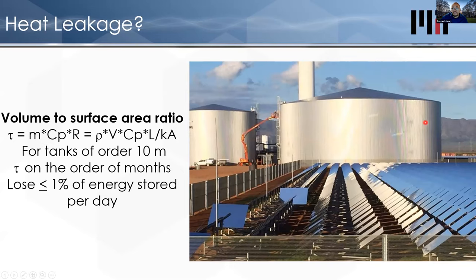So as you make a tank of something storing heat extremely large, this is order 10 meters in diameter, order 10 meters tall, it's got tens of thousands of tons of liquid salt inside. The time constant, the time it takes for this thing to cool down, is on the order of months. So you can heat it up and it's not cooling down. You won't measure much of a temperature change like a week later, right? Because the volume is so large. So you can lose less than about 1% of the energy per day as long as you're cycling your battery pretty frequently. The heat leakage can be negligible.